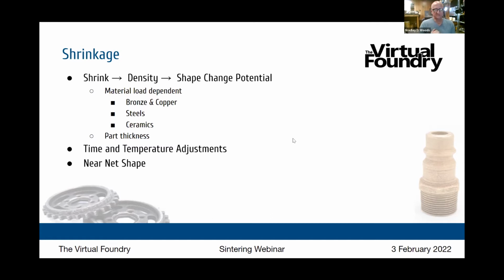And in many cases, our users just leave it here. This is okay. Other users need to have a very, very dense part. So you simply continue to sinter it. The particles, they don't melt, they diffuse further, and the part shrinks more and more. So by the time you hit shrinkage of about 20%, your part is about 98% dense. So the more you shrink the part to get to that 20% shrinkage, to get to that higher density, the more potential there is for that part shape to change.